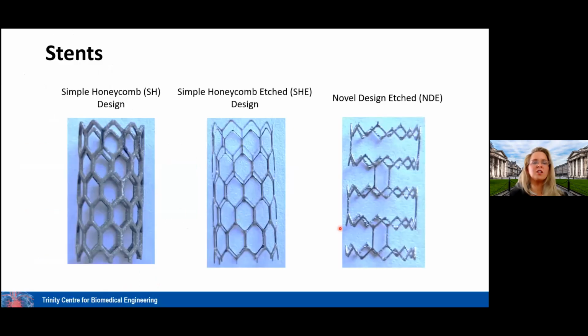So here are our three stent designs. Simple honeycomb etched is essentially this design with uniform thickness put into an etching solution to thin the struts and give us greater flexibility as well as improved surface finish. And here, our novel design etched, we just etched to the point where we remove the supports, and we see if that'll give us this open cell structure. And you can see that it does.